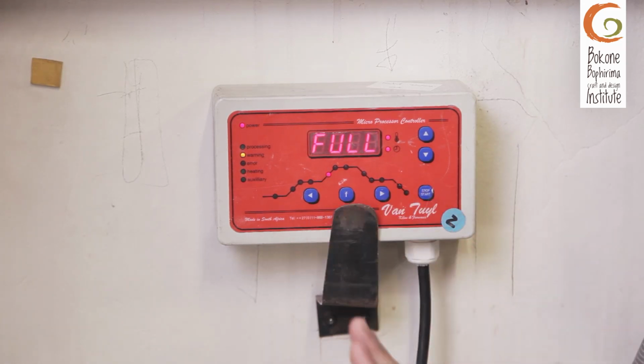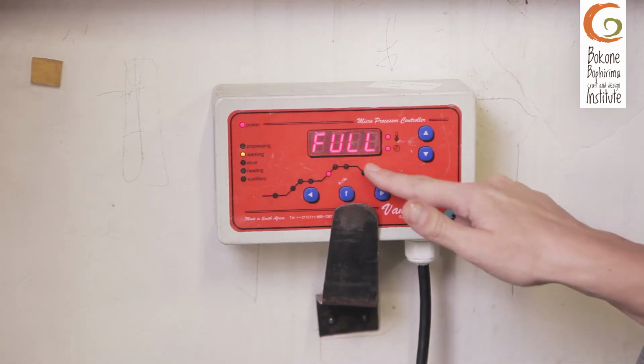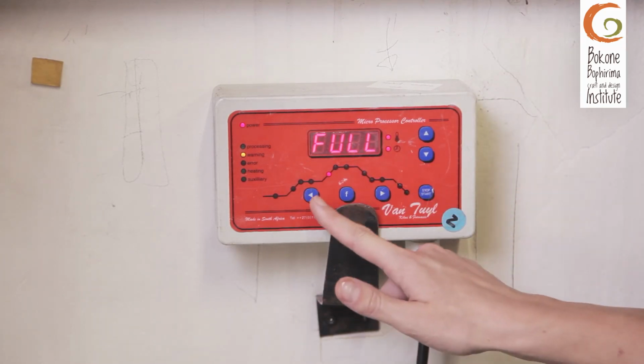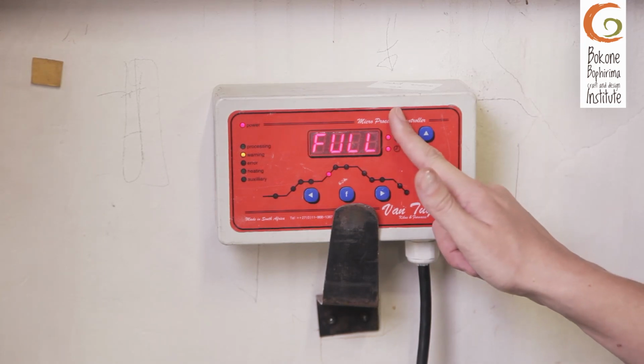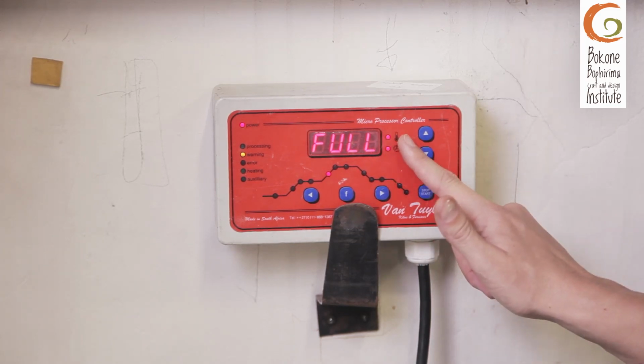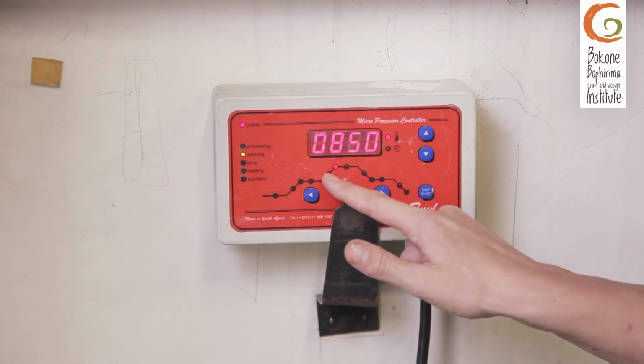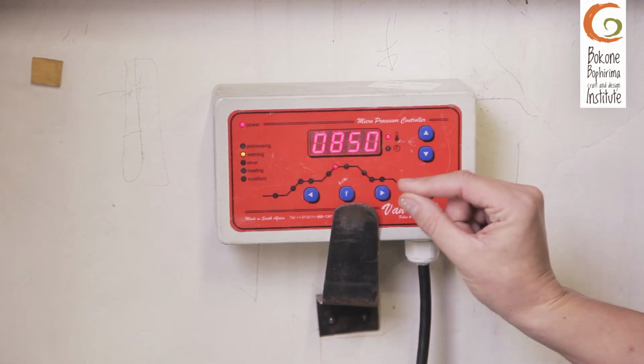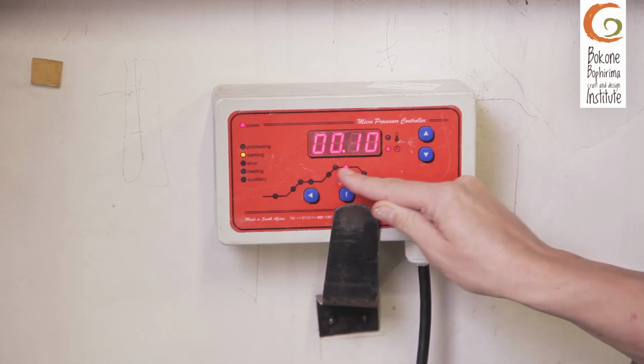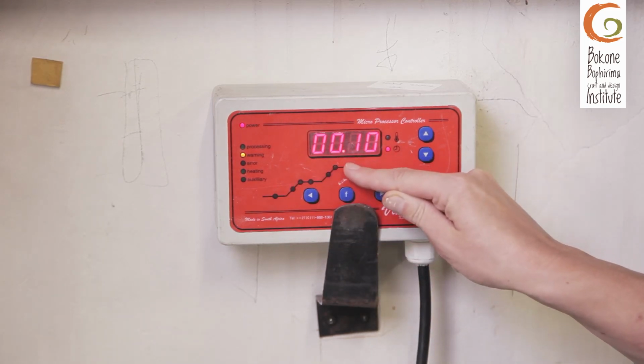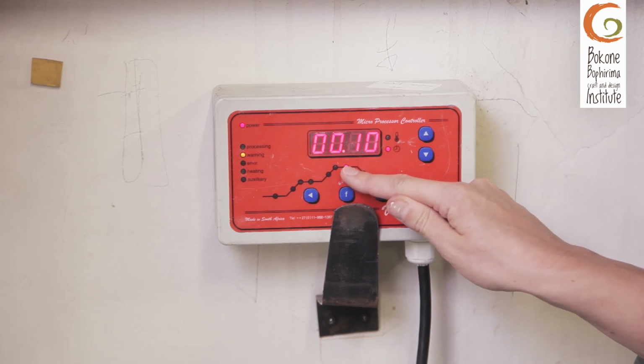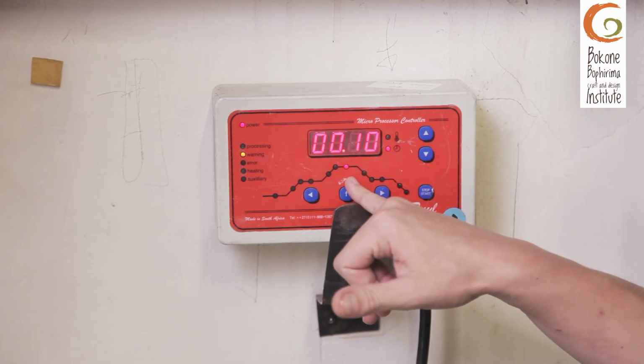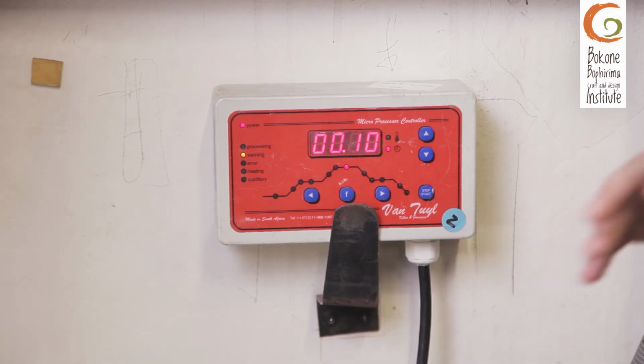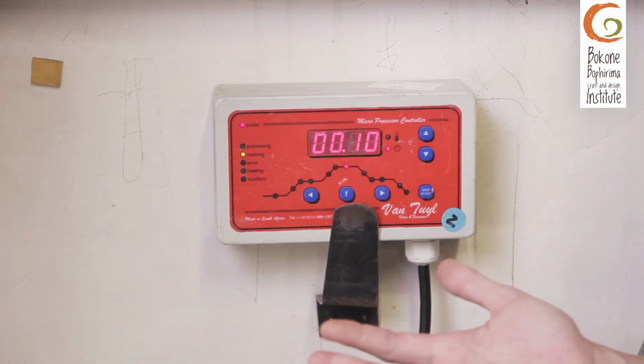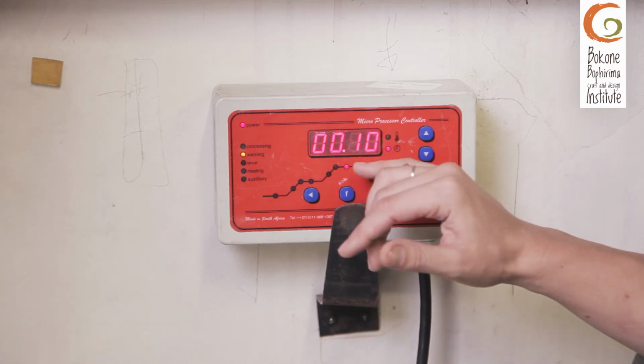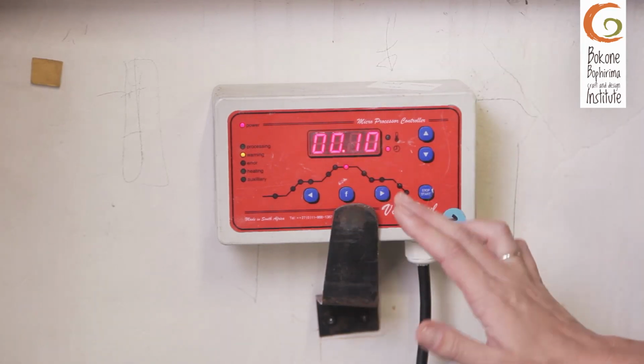Next process, now we're ramping up again, if you can see by what the picture is showing here. So now again we are working with time and temperature. So the time we want it to take up with the temperature till we get to our top temperature. Okay, then we have again a delay. So it's the same process repeated. When we are on this process here, often one is able to open up the kiln. Anything above I would say 680 is fine to open up your kiln to see what's happening, but never allow your kiln to drop lower than 680.